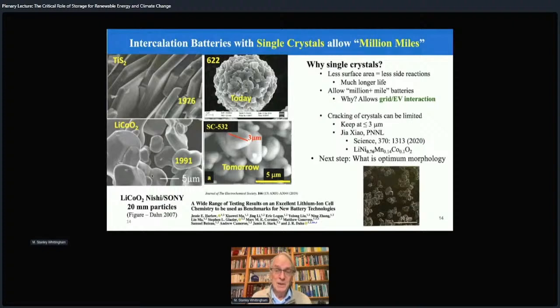That means we need lower surface area, so there's less side reactions. And we go back historically looking at what's happened in the past. Initially, at Exxon with TiS2, we used these single crystals. These are probably 100 microns long and about 5 to 10 microns thick. When Sony was making lithium cobalt oxide, they also used single crystals. This particular picture is from Jeff Dahn. Sony actually used single crystals of above 10 microns in size, again, to reduce the side reactions and to make their Walkman players and so on somewhat safer.